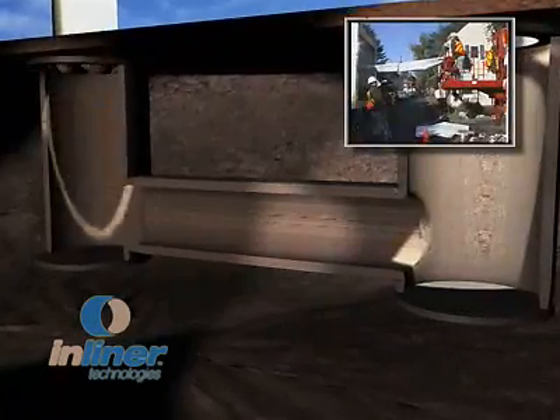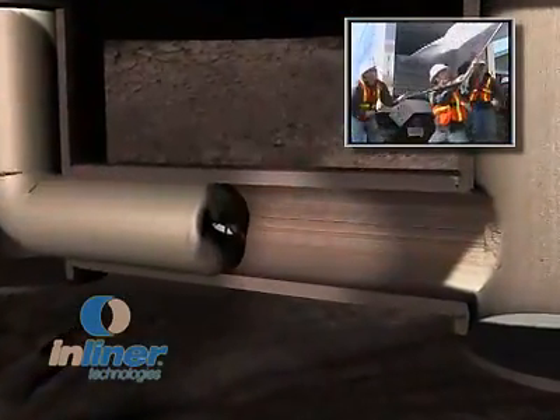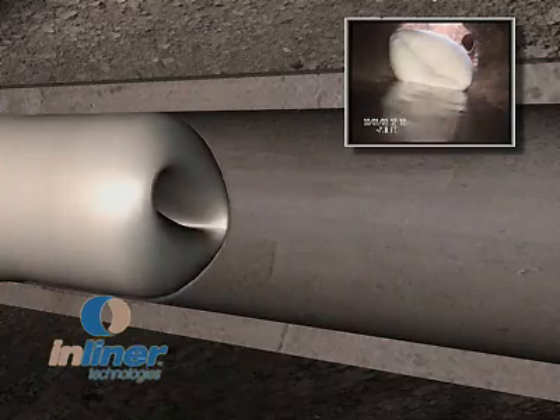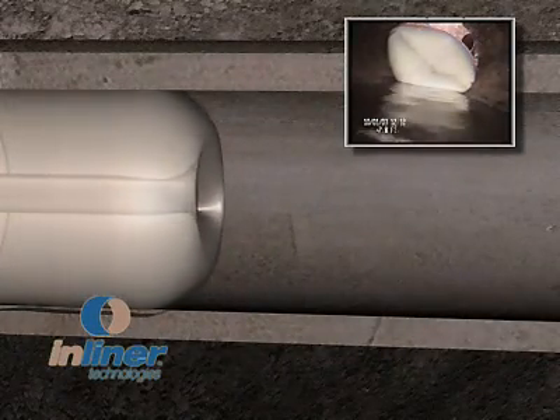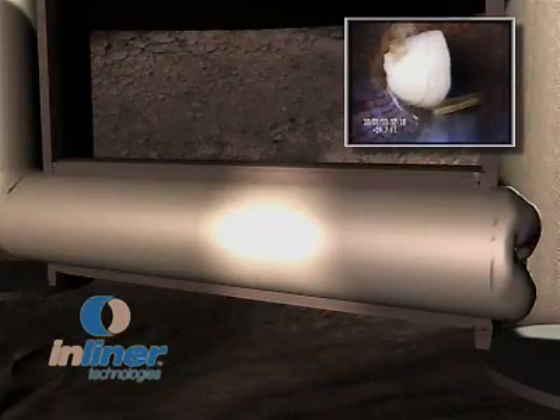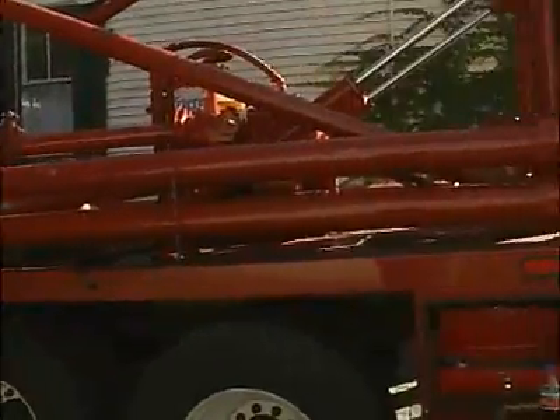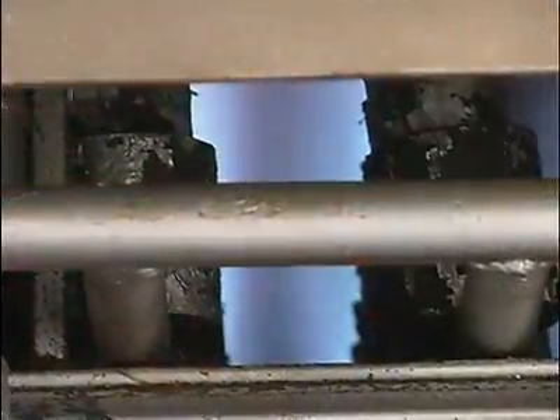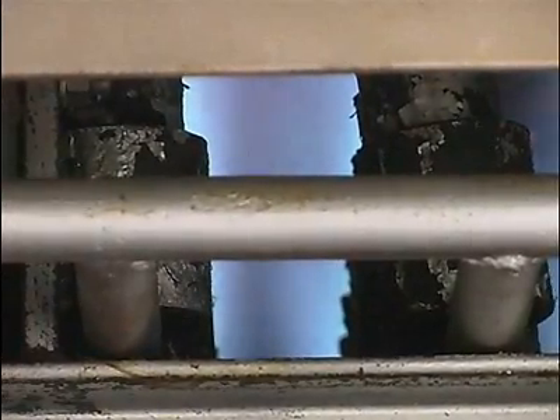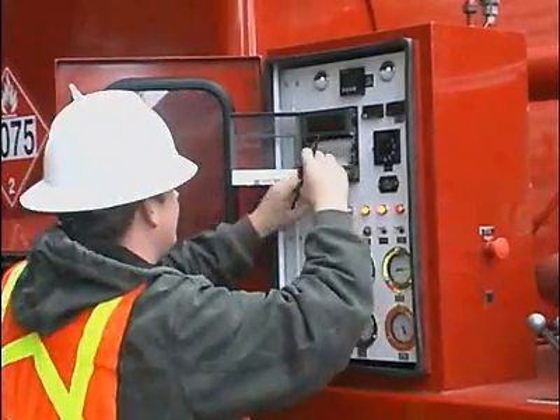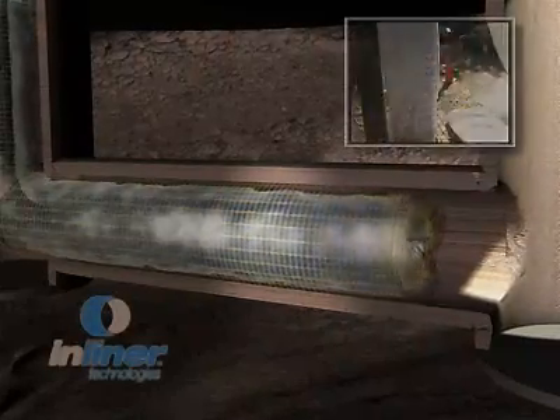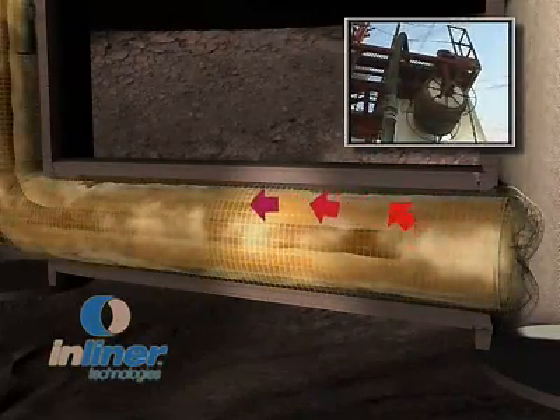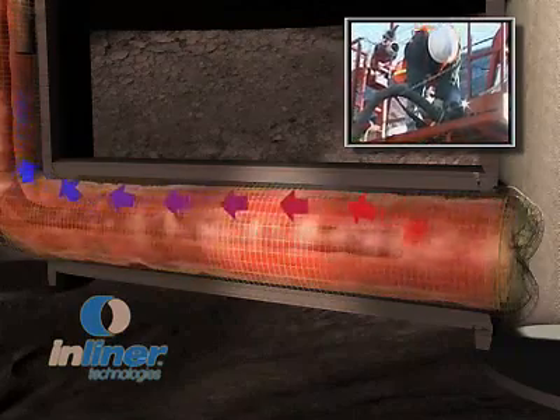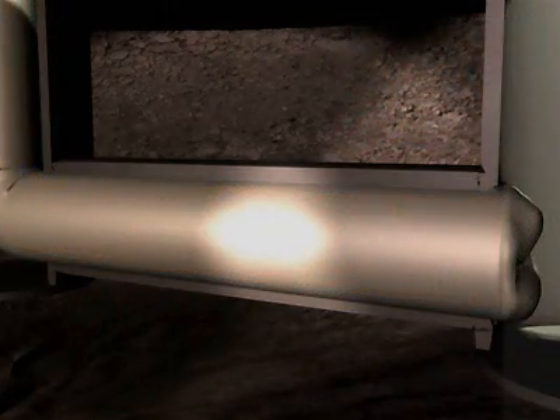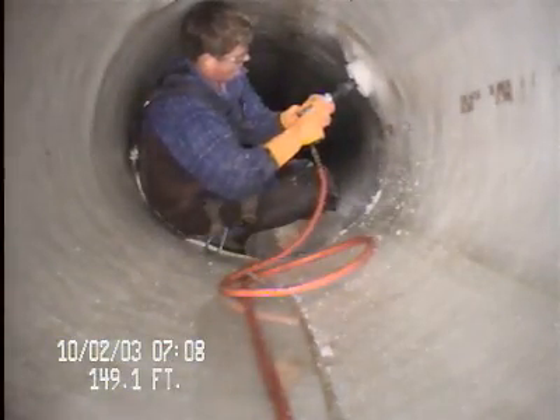The tube was inserted into the pipe, then inverted with water pressure. The water was heated to 180 degrees with an on-site heater truck. This is the temperature required to fuel the thermoset reaction between the catalyst and resin. Workers then circulated the heated water through the pipe for approximately 2 hours, completing the curing process. Once the cure was complete and the liner cooled, the service laterals were restored using a pneumatic cutting device.